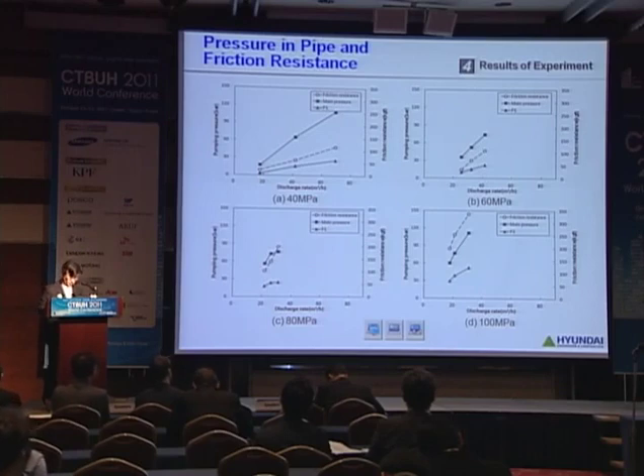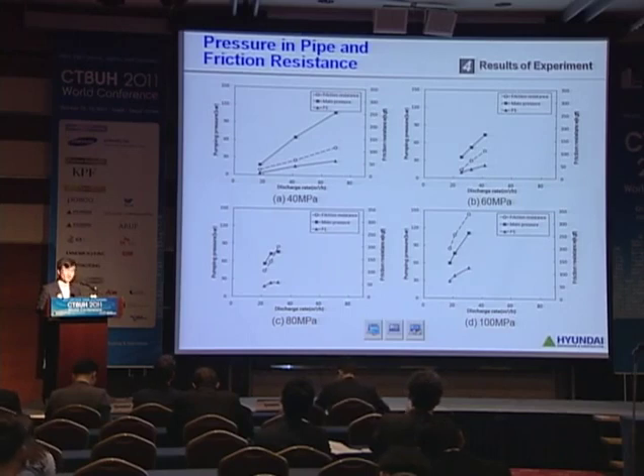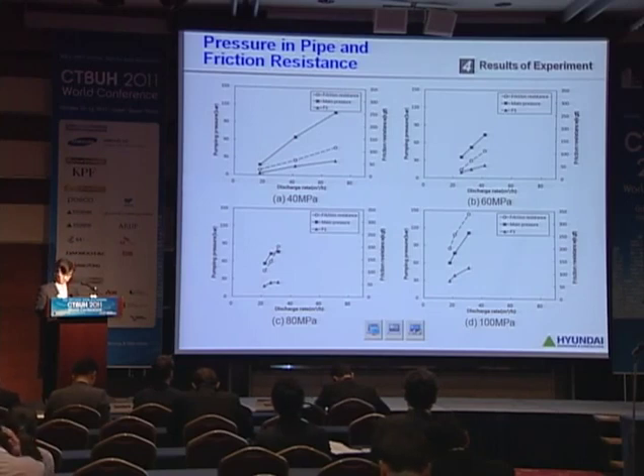This figure shows the relation between pumping speed and pumping pressure. In this graph, the x-axis is discharge rate of concrete as pumping speed, and the y-axis is pumping pressure and friction resistance. Pumping pressure and friction resistance tended to increase with the increase of pumping speed. From this result, it is considered that the increase of friction resistance is related to pressure in pipe.